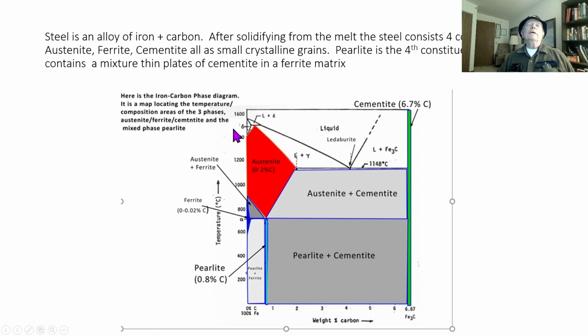Now, here is a reproduction of the iron-carbon phase diagram, which I have put colored regions on. It is a map which locates on the vertical axis temperature. So here we are with iron going up and melting at 1538 degrees centigrade, very, very hot. On the horizontal axis, it shows the weight percent carbon going up to iron carbide at 6.7%.